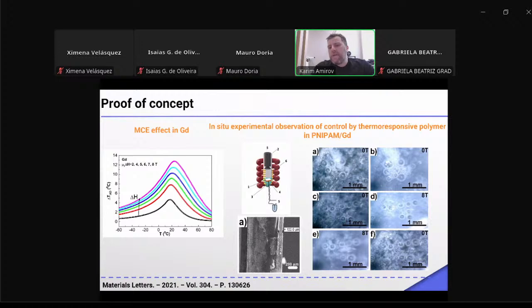A is in hydrated state and B in dehydrated state. And as you can see, that transparency is changing. And then we apply magnetic field. The polymer is heating as a result of the magnetocaloric effect. It goes to dehydrated state, and it's coming back. When you remove the magnetic field, then the reversible effect is observed.